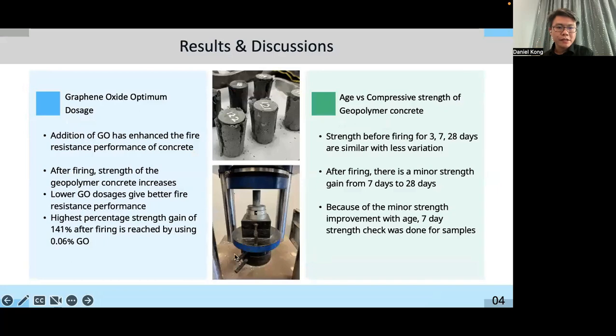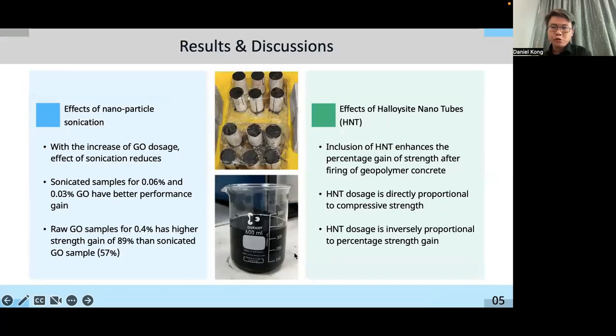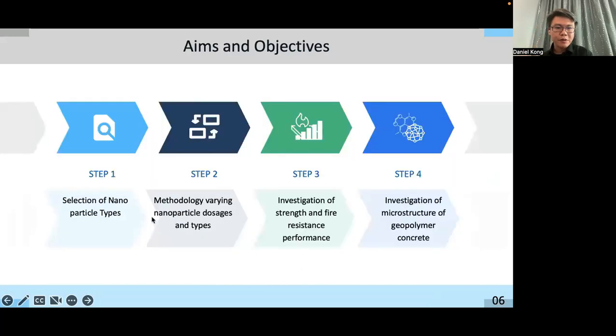So, showing you some of the things that we've done, there is a particular video that will show you how the process is done. I think that will probably summarize everything, but we've taken some steps to identify the nanoparticles to be utilized, and tweak the methodology to incorporate the nanoparticles into the matrix. And then, of course, the latter stages will be investigating its performance after elevated temperature exposure. Then we look at some of the microstructure to see what has happened. We've checked it for 3, 7, and 28 day strength. Just to give you an idea, this is just preliminary work. It's a 1-year project, so whatever we have is just preliminary.